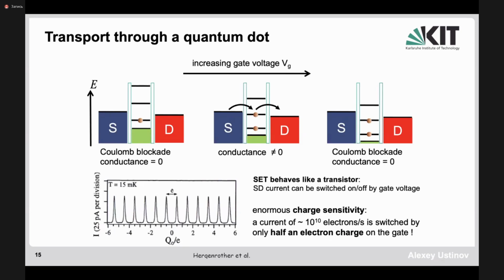such that conductance will occur if the source Fermi level is above the electron state level in the dot, but that one is above the Fermi level in the drain. So in this case, you have conductance, and you will have this peak in the current, as shown here, and you have Coulomb blockade if the state is below, since electrons cannot tunnel into the states in the drain electrode, they're all occupied. So you need to have some states above the Fermi level. And again, once you further change the voltage of the gate, then you will see that this state, which showed tunneling, will be blockaded.